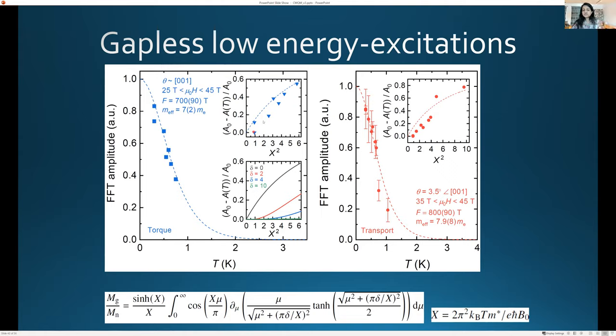And so we do a quantitative comparison. So the dotted line here has no variable parameters. The only variable parameter is the mass, which we've used to fit the regular LK, so it's 7 electron masses. So there's no other variable parameters. And you can see clearly that it's growing as you go to low temperatures, as you would expect for a gapless system. It looks nothing like what you would expect for a gap system. And I think this is actually a metric.